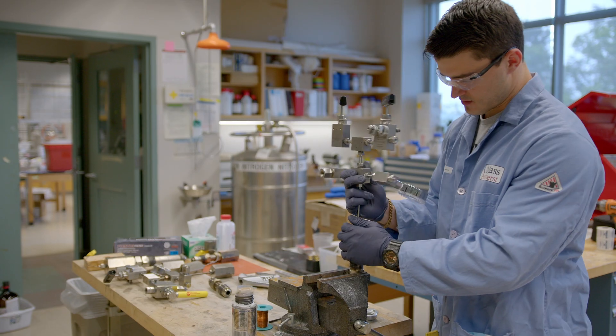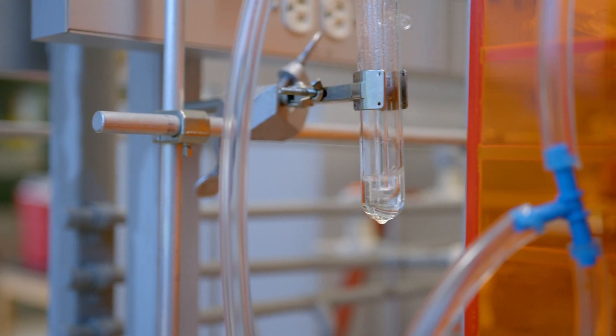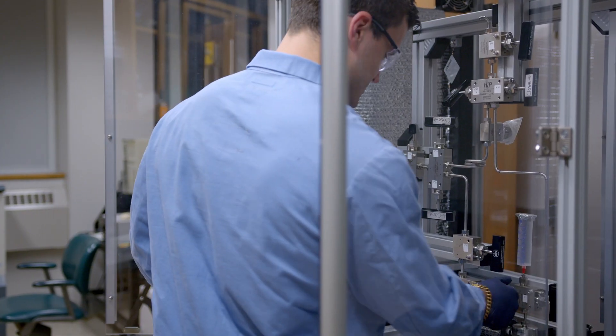Hello, my name is Alan Lesser. My research focus is really affiliated with mechanics and advanced manufacturing of polymers and composites. I enjoy working with unusual manufacturing methods like using crystallizable solvents that go in and plasticize the polymer during processing conditions, and then upon cooling either thermally or under polymerization undergo reaction-induced or thermally-induced phase separation to grow reinforcement through organic crystals. This allows advanced processing at lower viscosity while simultaneously achieving reinforcement.